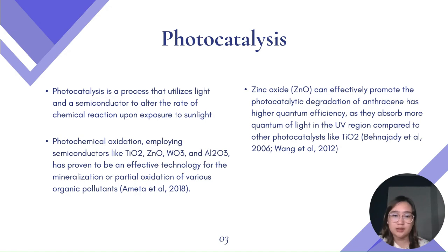Although zinc oxide has been widely investigated for photocatalysis in water to degrade organic compounds, limited research has focused on its utilization for the photocatalytic degradation of anthracene specifically. Recent experiments have demonstrated that zinc oxide, along with materials exhibiting longer transient times, can significantly enhance the photocatalytic degradation of anthracene. These materials also show higher quantum efficiency as they absorb more light in the UV region compared to other photocatalysts like titanium dioxide. Despite the relatively fewer research materials available for zinc oxide compared to titanium dioxide, they possess similar advantages.